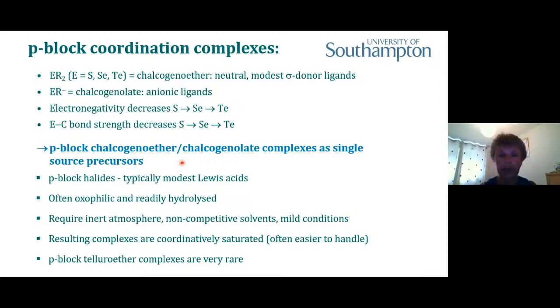These would normally be neutral complexes. And so we're often going to be using p-block halides, the p-block main group chlorides, for example, which tend to be modest Lewis acids. So that's compatible with our basic ligands. The p-block halides themselves are oxophilic and often readily hydrolyzed, so we need to think about our handling conditions, using inert atmosphere, nitrogen or argon, using vacuum lines and glove boxes for the synthetic part.